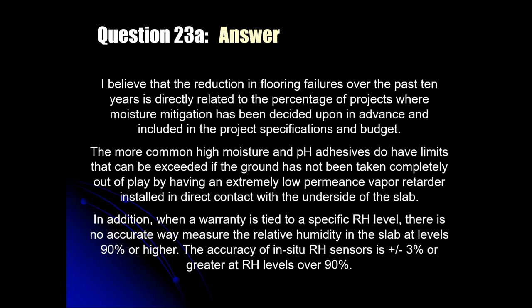It's next to impossible. If you have a warranty that says 90%, but the instrument that you're measuring relative humidity with has a tolerance of plus or minus 2 up to 90, and plus or minus 3 and higher at RH levels of 90 or higher, how do you prove what number it actually is? It gets to be a real fight when something goes wrong and the warranty is tied to a 90% or any relative humidity warranty in the 90s. Very, very difficult battle ahead.